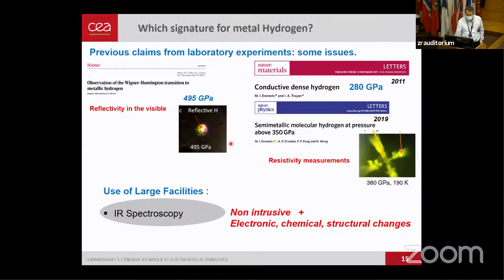And there are no measurements on the way going up to this pressure, on the evolution of the properties of hydrogen, so we can follow and be sure what has been measured. There have been other claims, putting electro-resistivity measurements with some leads on the sample. There could always be some problem: hydrogen is very active, forming hydrides, or the sample is very small and can be touching them. So there could be some problems.